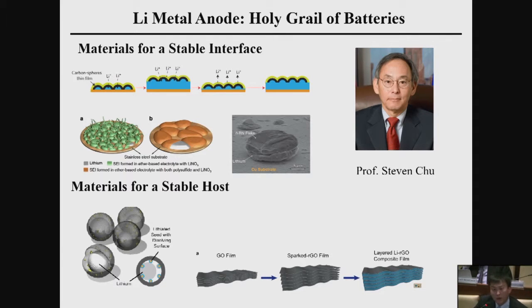We want to tackle the lithium metal anode problem. Lithium metal is considered the holy grail of battery research because it has the highest charge storage capacity, and it has the lowest potential as an anode, giving you high voltage in the battery and then high energy. However, lithium metal has a notorious problem. It grows dendrites, which short your batteries. So 40 or 50 years ago, when people worked on lithium-based batteries, they wanted to make lithium metal work, but they could not do that. And they actually burned down the factory, the battery caught fire. Now we want to revisit lithium metal and come up with a new idea of how to do that. Number one is to build a stable interface. So we have a few ideas, looks very promising. And to build a stable host, construct a home to contain lithium metal. Now it's becoming more and more promising. Hopefully in the next 5 to 10 years we can solve this problem completely.